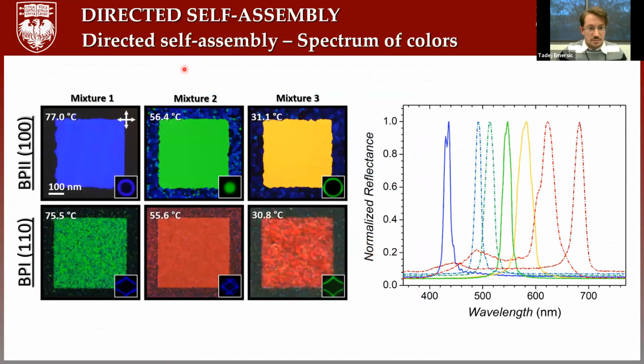So here are our results. For mixture 1, for mixture 2, for mixture 3, what we can see is that in all 3 mixtures, we can very nicely form single crystals of blue phase 2 with the lattice orientation 100. We can see different colors because we are dealing with different mixtures, and each of those mixtures has a different unit cell size, right? A different unit cell size, according to Bragg law, means different reflected light. We can see that in all these 3 mixtures, we can also form blue phase 1 with lattice orientation 110, but in this case, we have a granular structure. So in the other case, we form a monocrystalline structure.